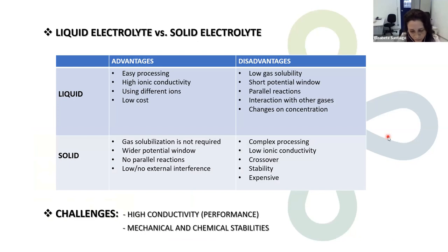In addition to fuel cells, solid electrolytes are gaining notoriety as an alternative in electrochemical devices, mainly those which use gas as a component. So the main difference between liquid and solid electrolytes is that in liquid we have as advantages easy processing, higher ionic conductivity, you can use different kinds of ions, and low costs, of course. But you have disadvantages such as low gas solubility and a short potential window caused by parallel reactions, especially the hydrogen and oxygen evolution reactions.